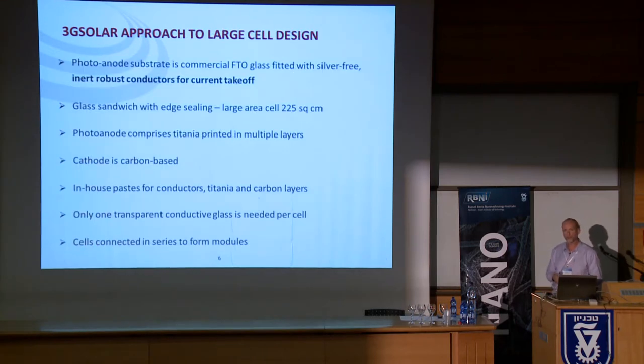We've also solved other problems to reach this very large dye solar cell size. We've created a very efficient seal for these cells — with organic materials and electrolyte inside it's not obvious you can achieve good durability, but our sealing system protects the materials very well. We've also improved output through a multiple-layer titania electrode, which is the active material with the dye that generates the charge.